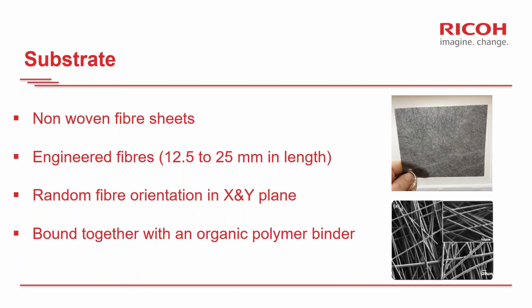As Mark has said, as we talk about composite material, we have two different types of materials that are used in this technology. The first one is the substrate, which could be either carbon fiber or glass fiber sheets at the moment. In the particular case of CBAM, the process uses non-woven sheets at the moment. These sheets are composed of long fibers that have a length between 12.5 and 25 millimeters. In the case of these sheets, the fibers are randomly oriented in the X and Y plane, as you can see in one of the pictures here from a microscope image, and the fibers are bound together by a polymer binder.